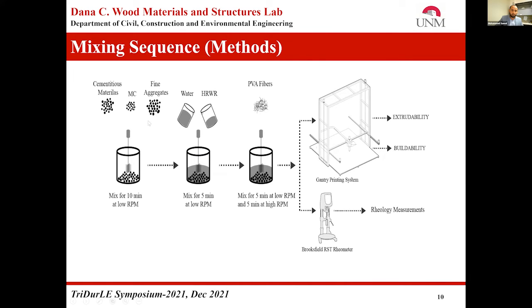This was the mixing sequence, which consists of 3 different stages. The dry material was first mixed for 10 minutes at low RPM, and then the solution of water and superplasticizer was added, and mixing was continued for 5 more minutes. In the last stage, the PVA fiber was added, and mixing was done for 5 minutes, followed by a 5-minute mixing at high RPM.